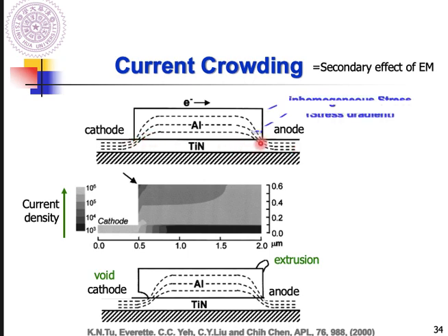And if you check the current density, definitely there's a stress field here, an inhomogeneous stress, right? Because the electrons definitely will accumulate here, and this density will be very large. So when you run the simulation of current density, you can observe this region, the current density is quite high, right? However, this region is quite low, lower by like 3 orders.